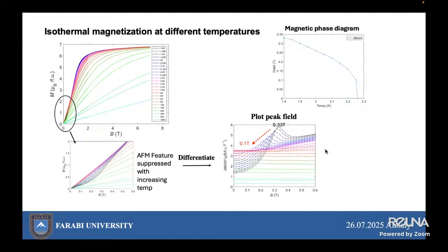Here you see the red dashed arrows track the peak field shift, tracing the magnetic phase boundary. And in the top right panel, the magnetic phase diagram is constructed by plotting the peak positions from this data as a function of temperature. It shows a clear downward trend, indicating that the field required to induce the transition decreases with increasing temperature, with a phase boundary temperature near 2.25 Kelvin, above which the antiferromagnetic order vanishes.